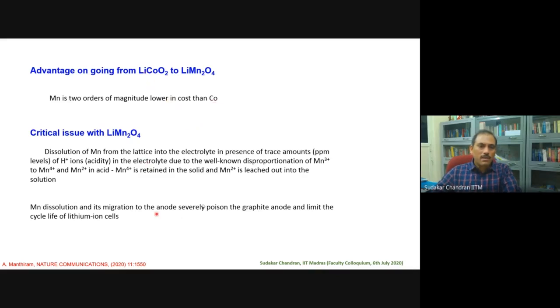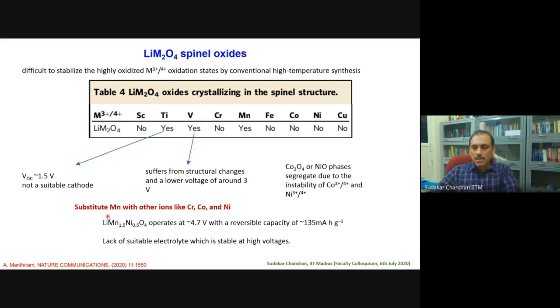But then there are other issues with this compound. The manganese easily dissolves in the electrolyte. It undergoes a disproportionation reaction. Manganese 3 plus would become 2 plus and 4 plus, and 4 plus is retained in the solid, and 2 plus gets leached out in the solution because of the electrolyte. And also these 2 plus get shuttled to the anode, where it gets coated, and therefore you have a limited cycle life. So there are many issues.